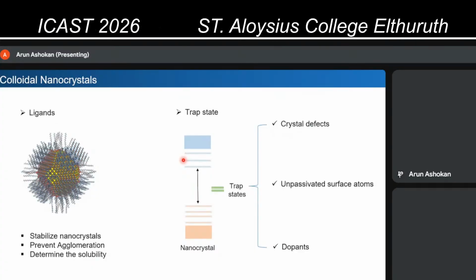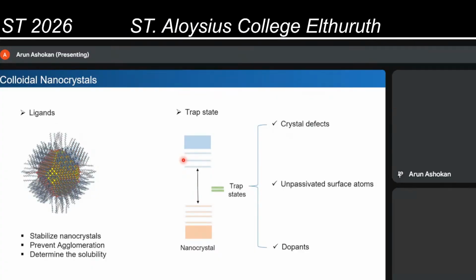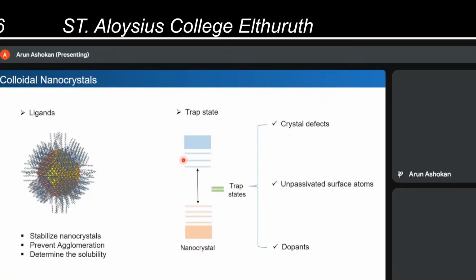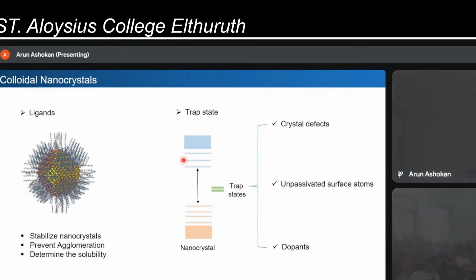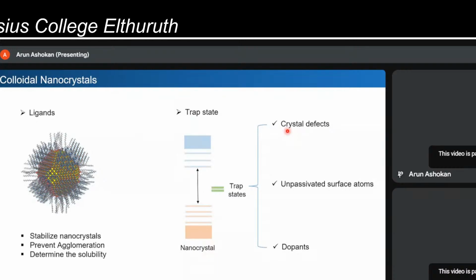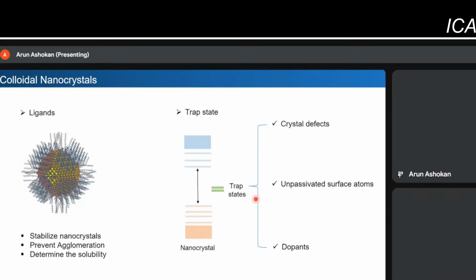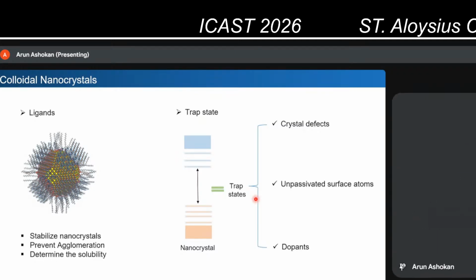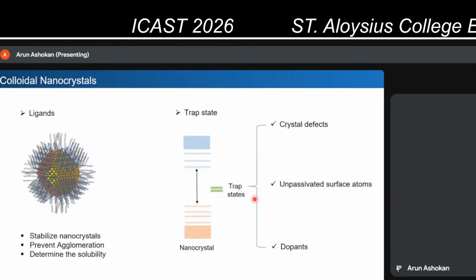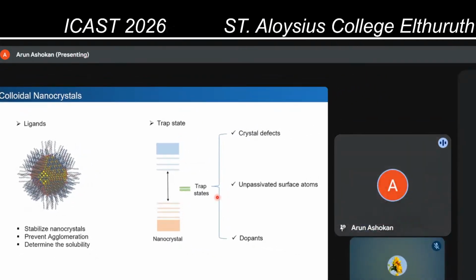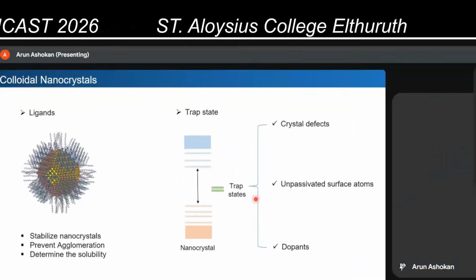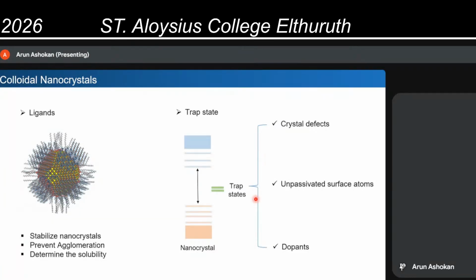When you make these nanocrystals, basically they are ordered solid, but there can be some defects which you might have known before where we have studied. That can happen. They can create some intermediate energy states between the conduction band and the valence band. And also, as I said, there is a lot of surface atoms, and the surface atoms are not stable. So this can also create trap states. And finally, you deliberately add some hetero atom to create these intermediate states. These are called dopants. You might have heard about it.